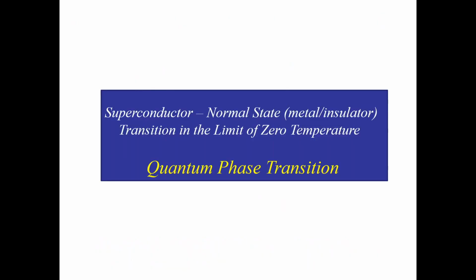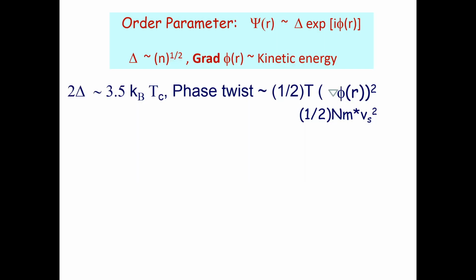All right, so now we look at the superconductor normal state or superconductor insulator phase transition in this system in the limit of T equal to 0, the zero temperature quantum phase transition. Now, if we look at the superconducting state, we have the order parameter. The complex order parameter has two parts: one is amplitude and the other a phase. Amplitude is equal to the square root of the condensate density, and the gradient of the phase gives us the kinetic energy of the superfluid.